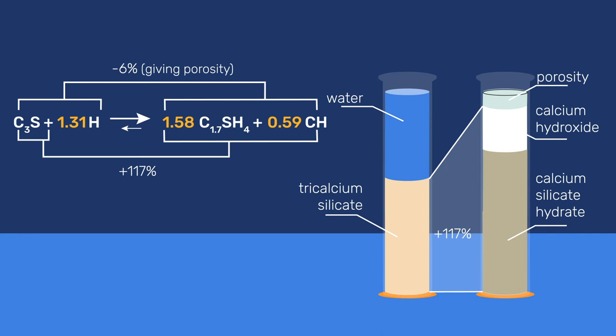As for natural cement and pozzolanic mortars, the hydration reaction can take place in absence of air. The hardening of these binders does not result from the losing of water through drying, but rather from the binding of water into solid phases through chemical reactions.